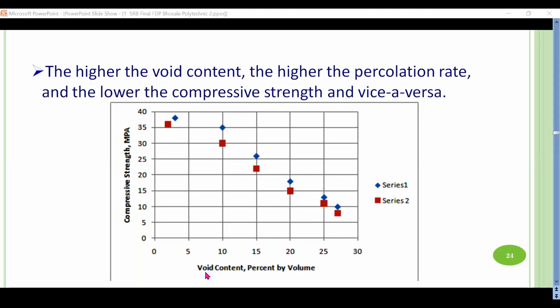Another graph shows compressive strength and void content. We already know that for ordinary concrete, as void increases, the compressive strength decreases. This is true with pervious concrete also. You can see here when voids are very low, 2 to 3%, the compressive strength achieved is 35 MPa, whereas when the void content increases, the compressive strength decreases. Now depending on the application of pervious concrete, let us say heavy loads are there, or as in the earlier slide, light vehicular traffic is there and it is expected that 30 MPa should be the concrete strength, then only a 10% void content will be there. As this is less than 15%, the permeability will be almost zero. So we have to decide upon these parameters while going for mix design of pervious concrete.